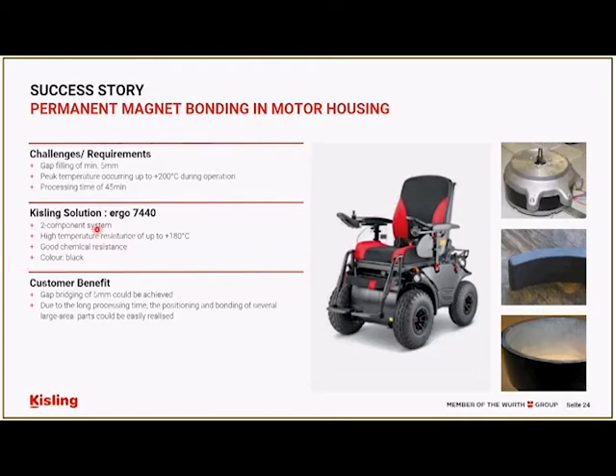The recommendation here was our two-part system, ergo 7440. High temperature resistance was met at 180, excellent chemical resistance, and also it was black. Gap bridging of 5 millimeters could be achieved easily, and the whole application was realized in a timely manner.